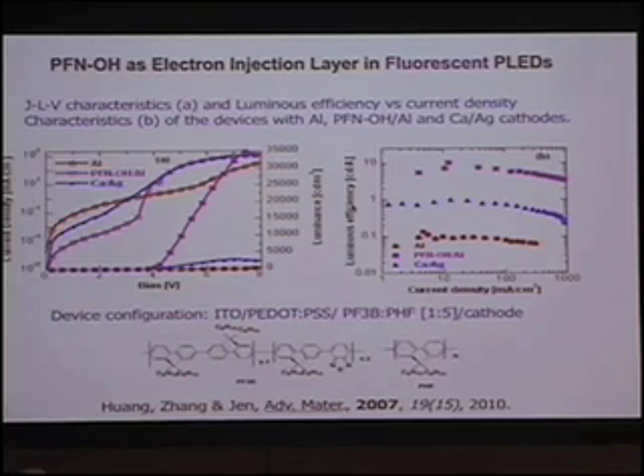Okay, and on top of this, two types of cathode are used. One is based on a very low work function metal like calcium, and the other is aluminum. Aluminum has a work function of 4.2 eV, much higher than calcium, so you have a much higher energy barrier for electron injection. But then we have this conjugated surfactant. With aluminum only, compared to that, you have about two orders of magnitude difference in device performance for electron injection, and also much higher brightness.